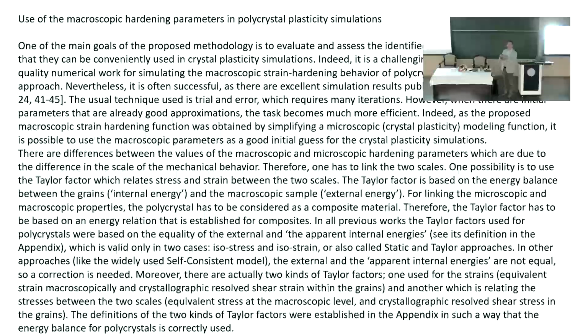And we get even the so-called orientation distribution of the crystals, the grains which make the polycrystal, that you can also compare with the experiment. It was measurable in experiment, and one can also follow its evolution by simulation. And if all this is agreeing, then you are doing good science, and you will get understanding.